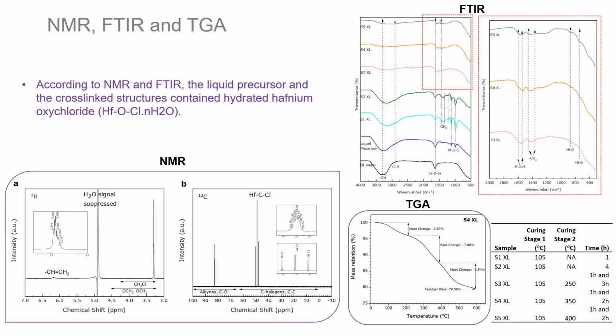Several characterization techniques were used to evaluate the polymer to ceramic evolution and microstructures in hafnium carbide ceramics, and some of those characterizations are presented here. The polymer precursor was investigated using liquid state NMR to determine the molecular structure of the precursor. In addition, FTIR was utilized to determine the polymer structure of the precursor and also the transformation of the precursor from liquid to cross-linked samples at different temperatures. Now, according to NMR and FTIR, the liquid precursor contained hydrated hafnium oxychloride.